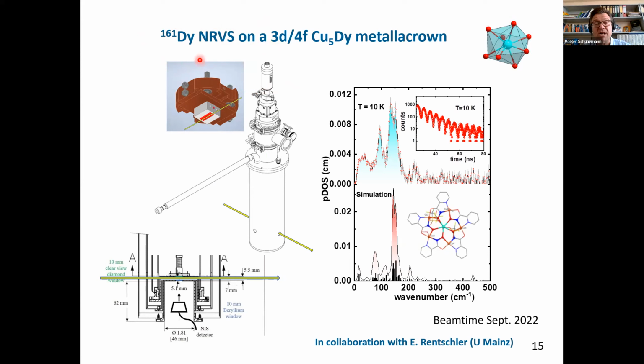We couldn't measure, we couldn't come to Argonne, but luckily last September we could go there, and we brought a new cryostat which allowed measurements down to 4.2K, and adjusting the APD detector very close to the sample, actually at a position of 5 millimeters. So the sample was at 4.2K, 10K, like we wanted to have.